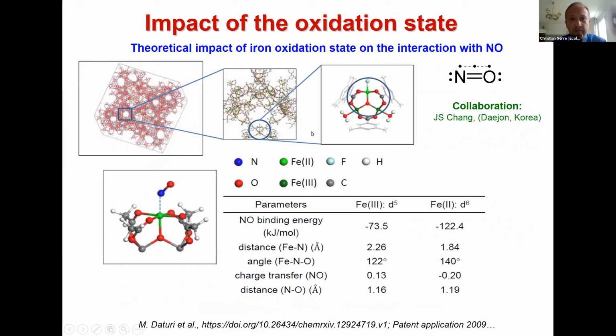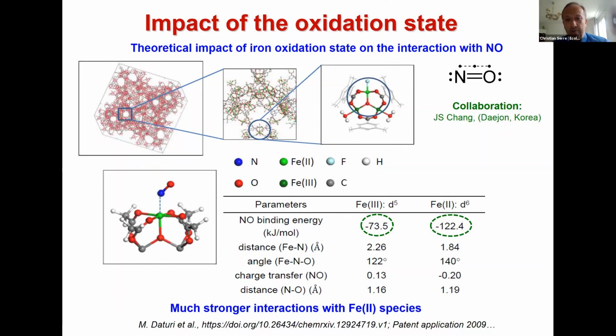Why do we have this? These are calculations done a few years ago by Korean colleagues. They estimated the binding energy of NO on the iron 3 d5 and on the iron 2 d6. You can see here that when you have d6, so an additional d electron, you increase the binding energy of NO on the metal site by almost 50 kilojoules per mole. So it confirms the origin of this stronger interaction with the iron 2 metal site.